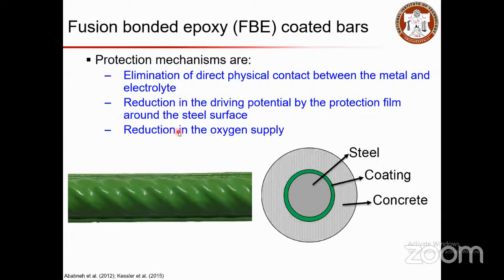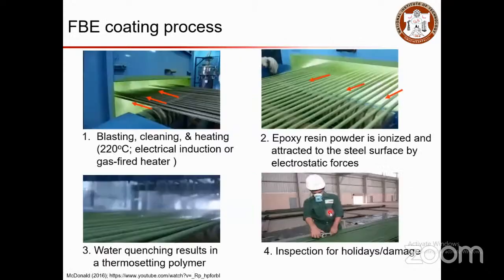So the concept here is that the protection mechanism eliminates the direct contact between the metal and electrolyte, and reduces the driving potential through the protection film around the steel surface. When you have such arrangements, there will be a reduction in oxygen supply. So people thought these things would be very good to protect your steel, and this protection technology has come up. You can see a lot of manufacturers in India who use this FBE coating process as well.